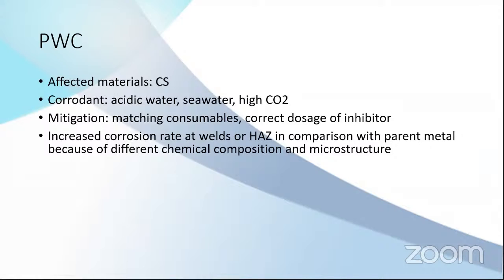The reason is that weldments have a different chemical composition and microstructure than the parent metal. So when the consumables used are not similar, not close to the parent material, it can be preferentially attacked. It might have a lower corrosion resistance than the parent material, so it gets attacked even more because of galvanic action.